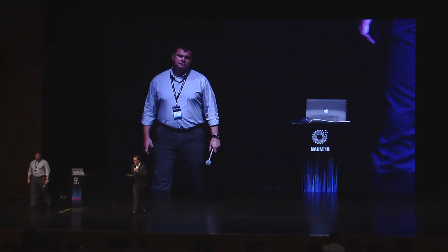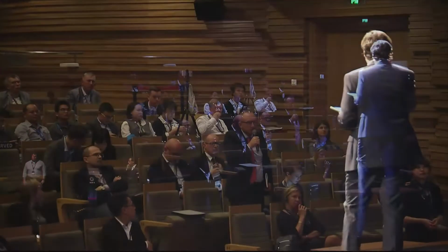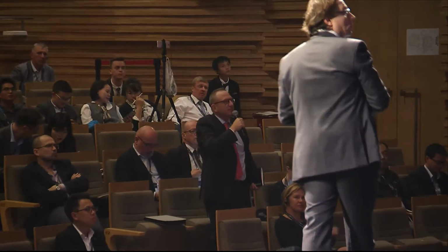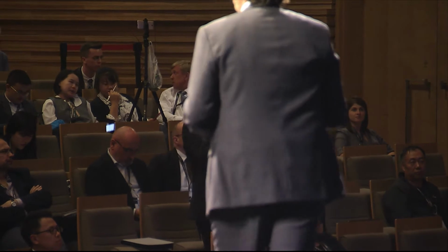Scott, when you talk about moving that technology over to lithium-ion, what do you expect the improvement to be? Is it energy density? Is it C rate? What do you expect the improvement to be in the lithium-ion system? I expect it to be in C rate, improved rate performance of these materials. Effectively, with a better conductive network, you have better charge distribution through your particles as well as your cathode, and that would tend towards implying that you're going to get a better rate performance from your materials, or alternatively, a higher efficiency at higher discharge rates.